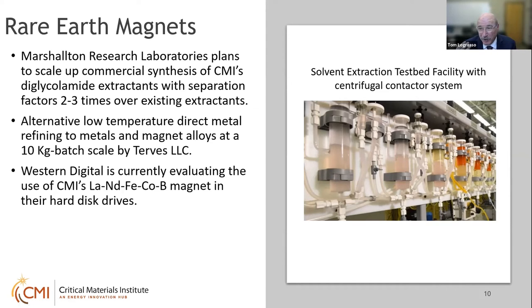We also develop alternatives. In this case, it's a neodymium magnet, but it has about 25% lanthanum substituted for the neodymium. So about a 25% reduction in the critical rare earth. We do have to add a little bit of cobalt just to compensate. Lanthanum is not one of those magnetic rare earths, but Western Digital is quite interested in evaluating the use of this alternative reduced critical rare earth magnet for use in their hard drives. Western Digital also, as many of the tech companies, is concerned about the end of life. And so they come to us looking for better ways for recycling and disposition of their hard drives. How can they be good stewards, even if they're not doing the recycling themselves, and ensure that their materials and their products are being managed responsibly?